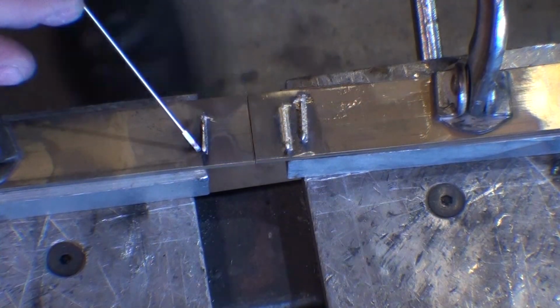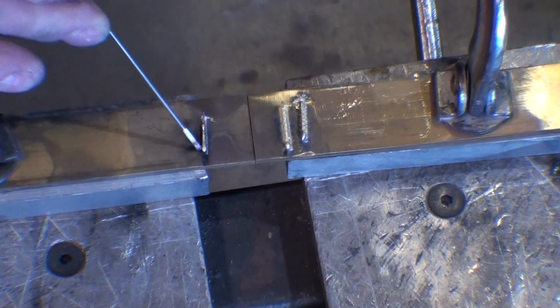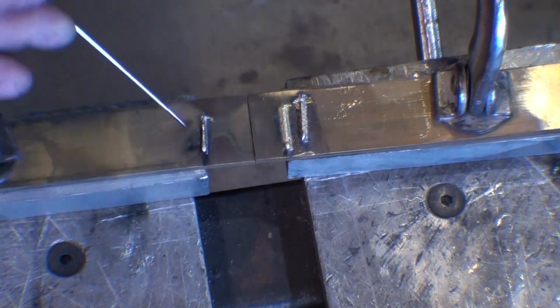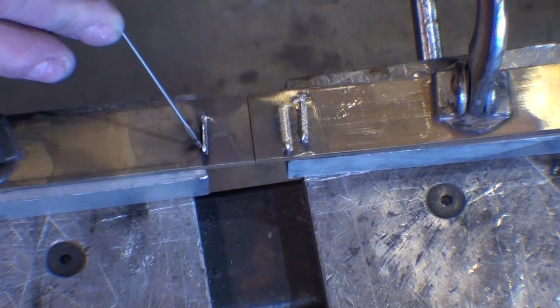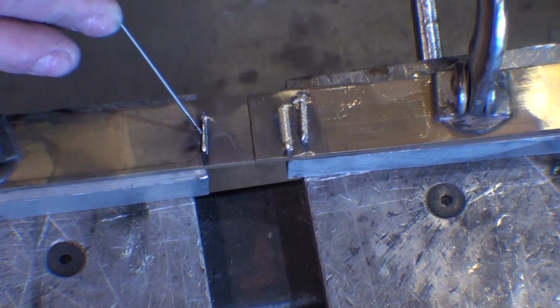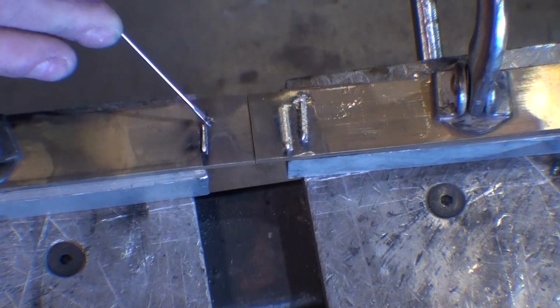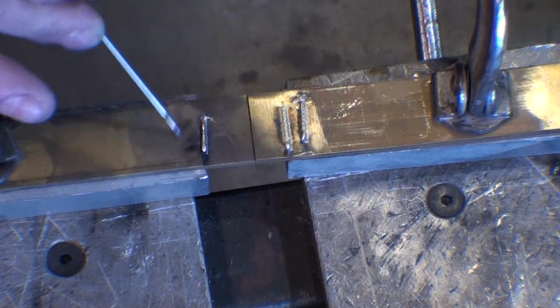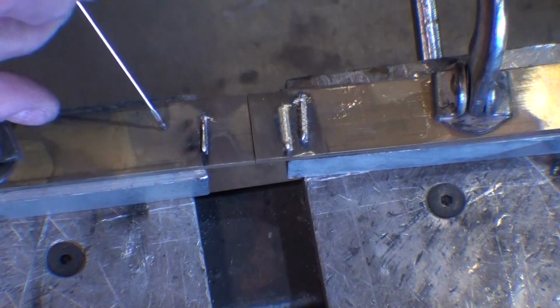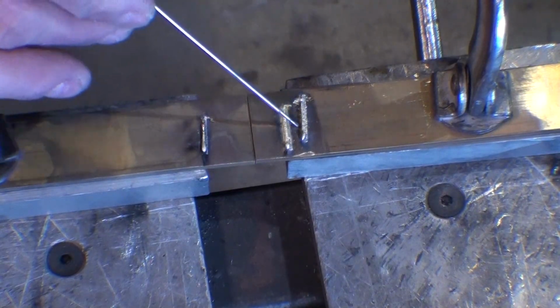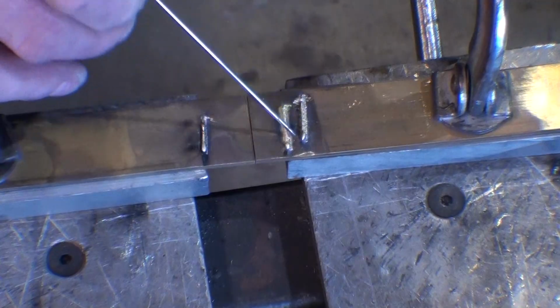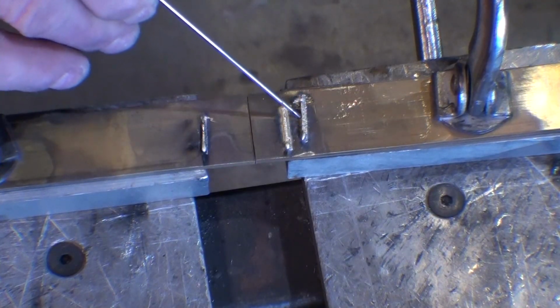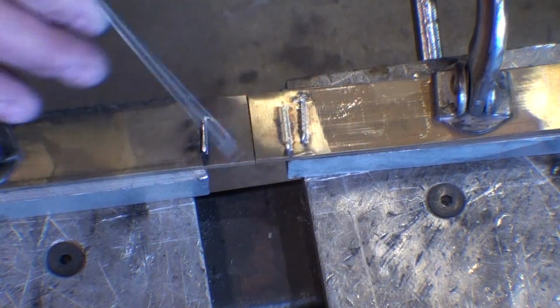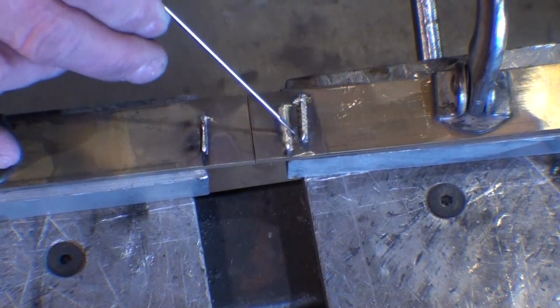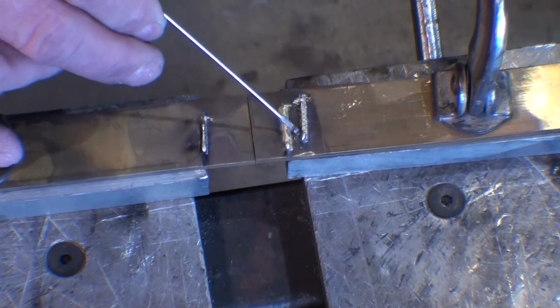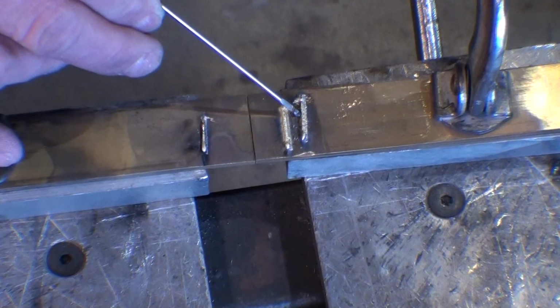So over here, I'm testing. I'm starting at the low point and keep stepping up. So 300 power range, the wire barely melts. Okay, so kind of just glued it to the surface. Now the next one was a little bit over 400. Same results, but my wire tracked a little bit on the wrong side, on the right. So I blasted the base material, melted the wire a little bit, but just not enough.